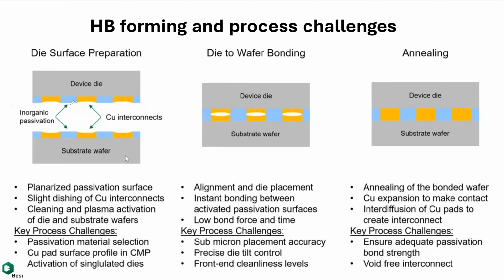Sometimes they use other materials, but the mainstream is SiO2. It's easy, and there's a lot of experience with it. People sometimes use silicon carbide or some other material. Some even use carbon nitride. We'll talk about that in one of the photos. And then you want to connect the copper. The copper has to form a concave, a little bit lower than the dielectric edge, so that when they bond, they form a kind of small void.